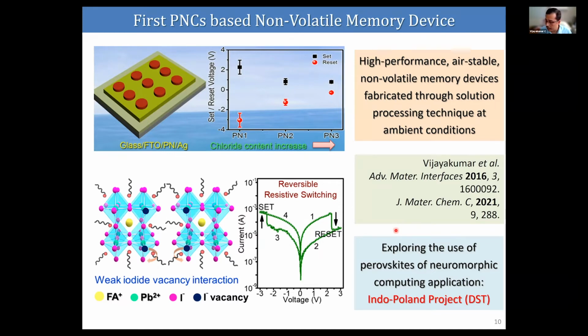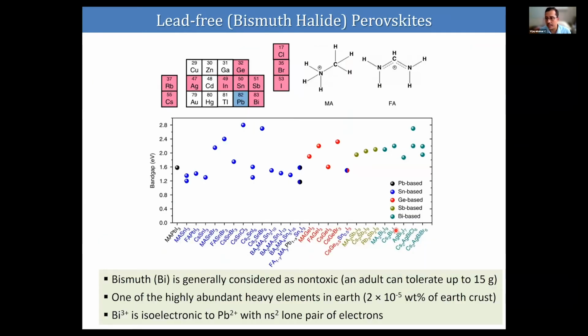So now coming to the main topic of today's lecture, that is lead-free. As I said, we are currently working on bismuth halide perovskites, and you can see the major metals used for developing perovskite. Lead is the major one, and we can use tin or germanium because they belong to the same group. Similarly, we can use bismuth and antimony, and we can also develop double perovskite by using indium and silver.